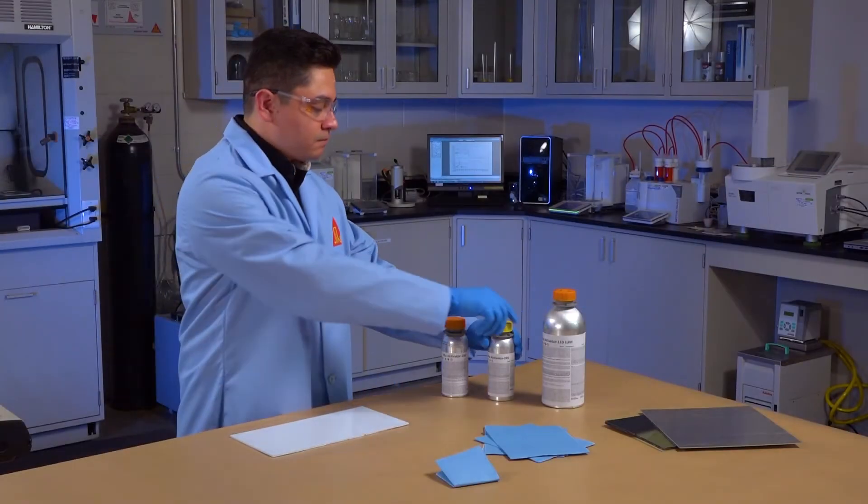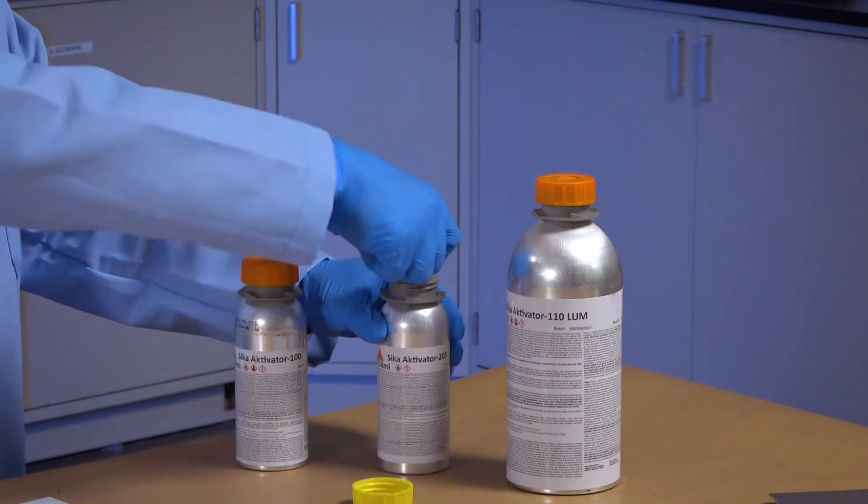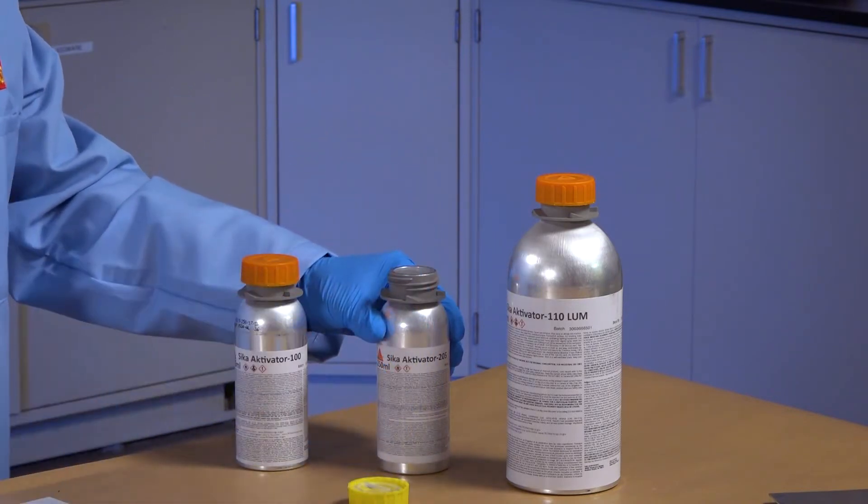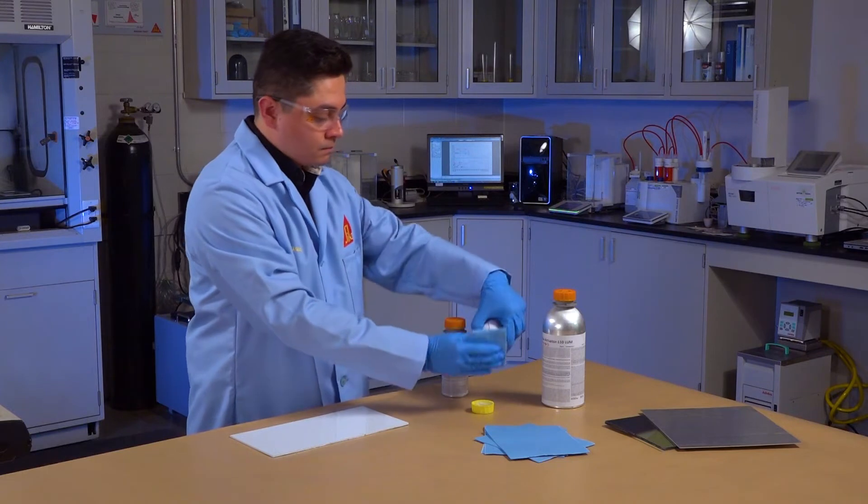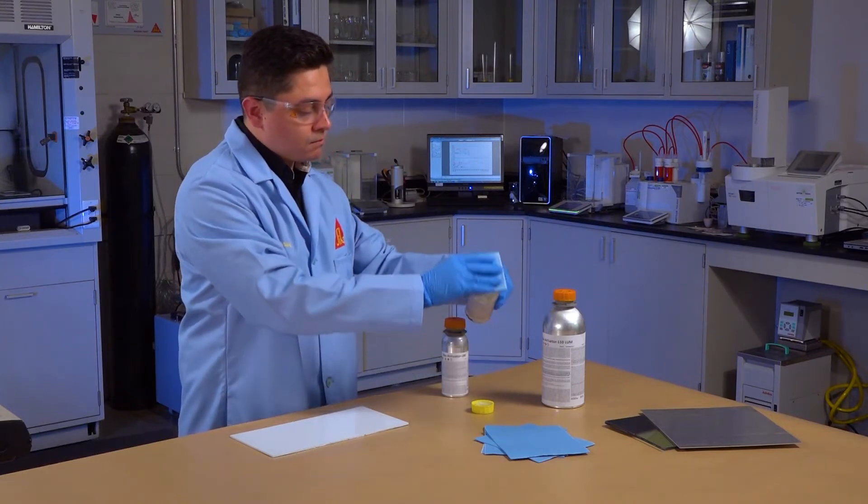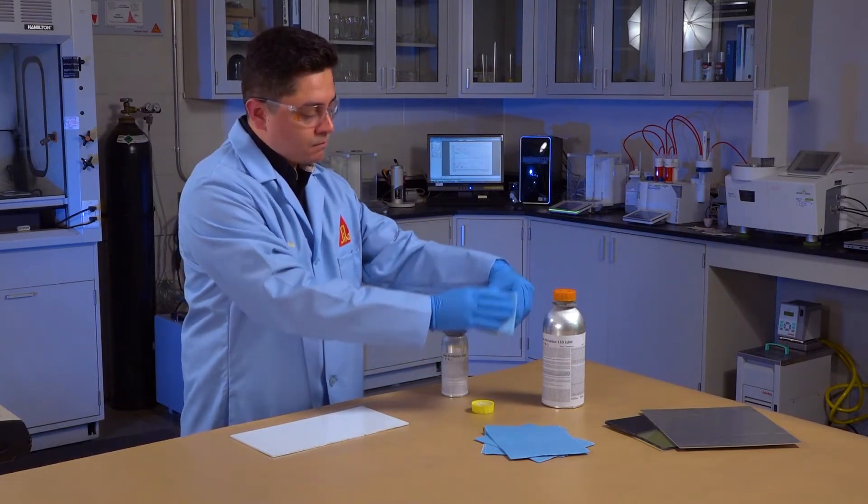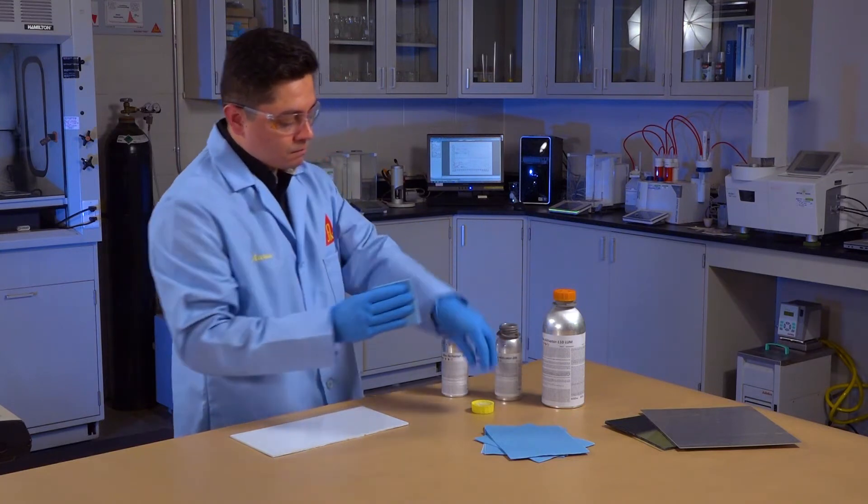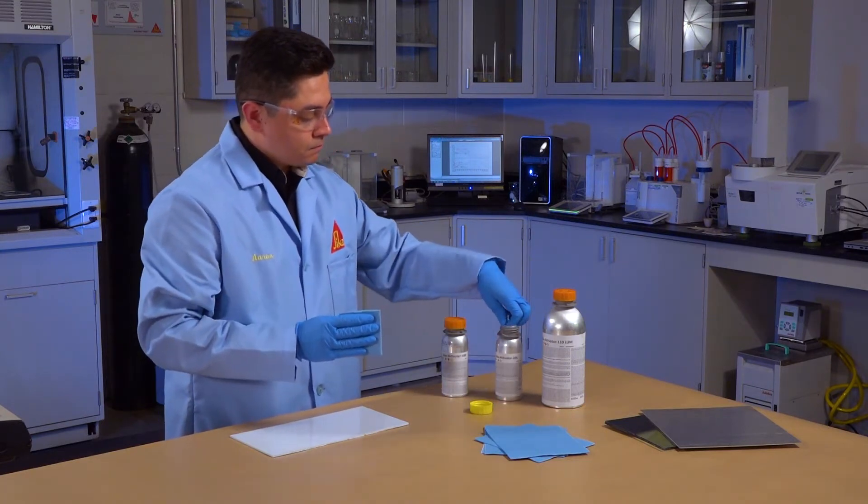Some Sika Aktivators require a wipe-on and wipe-off method, while others are applied using a wipe-on only technique. Always refer to the corresponding product datasheet to determine the correct method of application. Each surface activator has a minimum and maximum flash-off time prior to the primer or adhesive application. This time must be strictly observed.